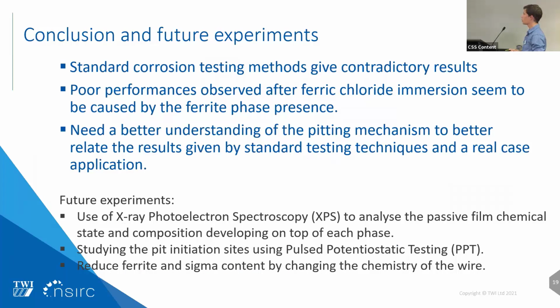So in conclusion, we can see that for the WAAM material, we have standard testing techniques that give contradictory results. When we look at potentiodynamic or CPT tests, which are done in the industry, we might think that we have a more corrosion-resistant alloy compared to a wrought 316L, where in the end, as we've seen with pitting potential and pitting tests in ferric chloride, this is really not the case.